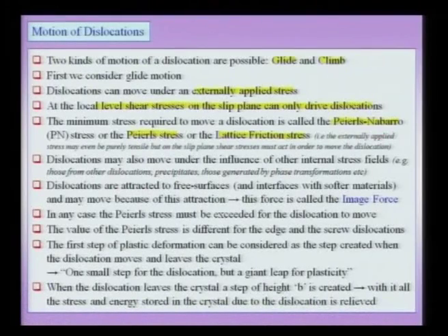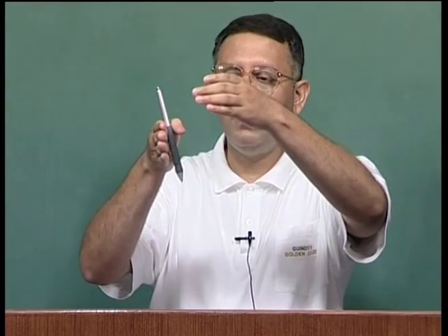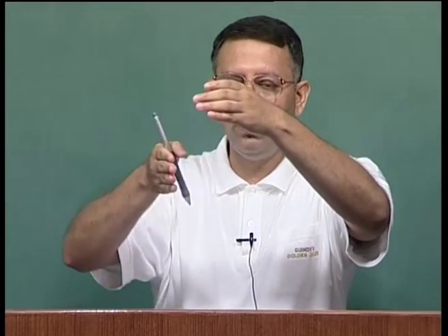And as we already know, you might have a tensile specimen and you may be purely applying a tensile load, but at the microscopic slip plane level, if you have a cylindrical tension specimen for instance, the horizontal plane and the vertical plane do not have any shear stresses, but every other inclined plane would face a shear stress, and therefore these shear stresses can drive the motion of dislocations leading to plasticity, which is what we see as the plastic strain when you do a uniaxial tension experiment.